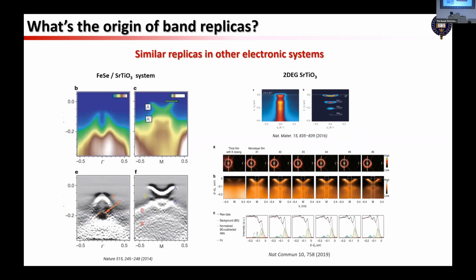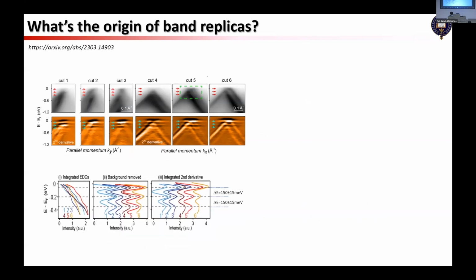And this is quite similar to other 2D systems like iron selenide on the strontium titanate substrate, or the 2DEG on strontium titanate system. So that motivated us that this probably could be caused by some sort of boson, but what boson, right? To figure it out, we did some more analysis and found that the replica and the flat band are evenly spaced, and the energy separation is around 150 meV.